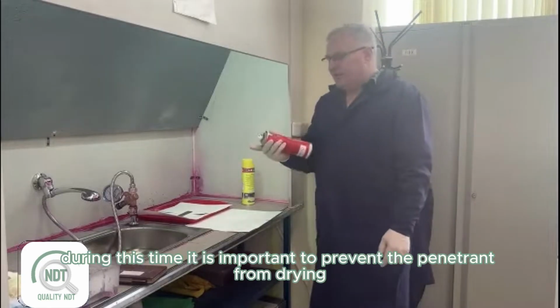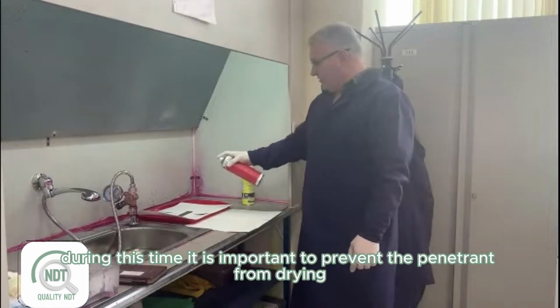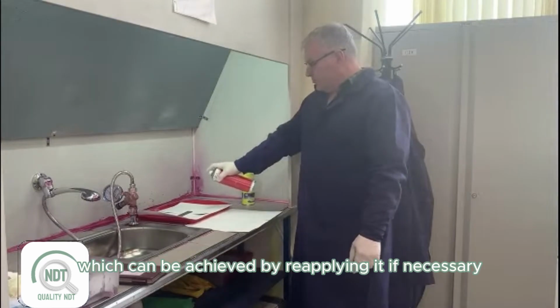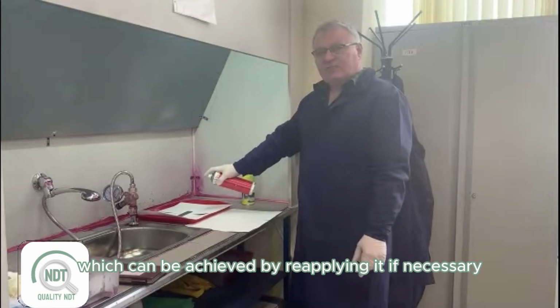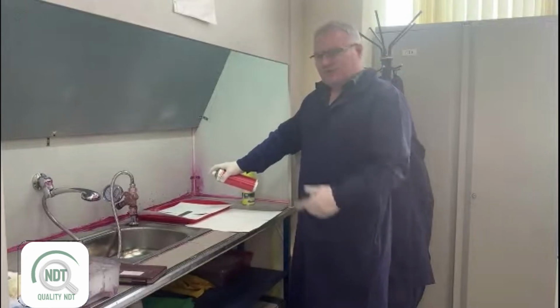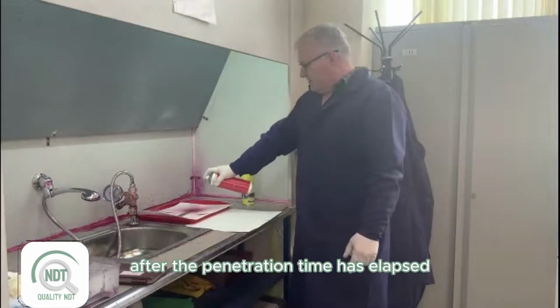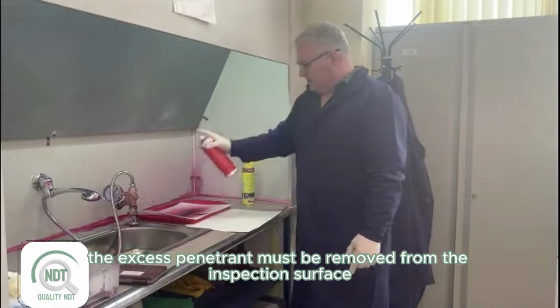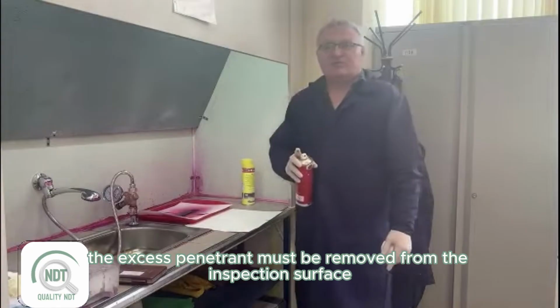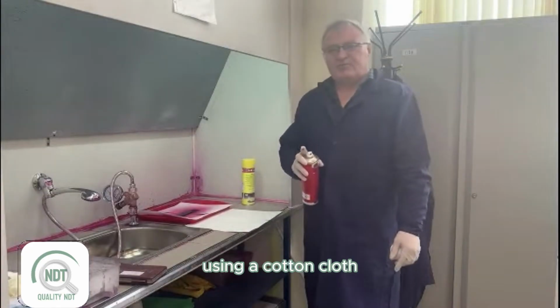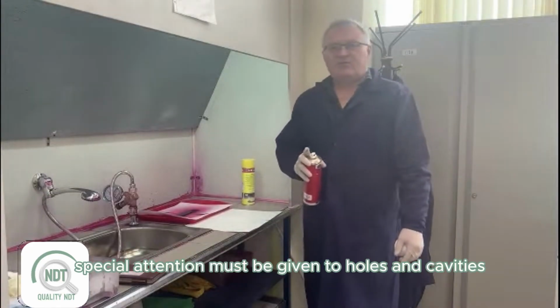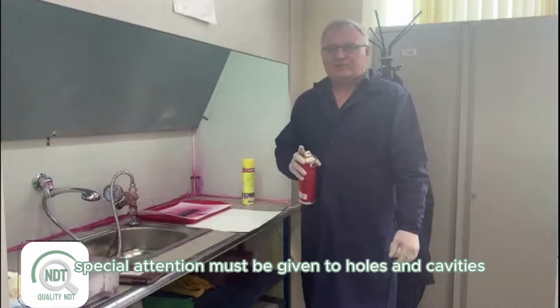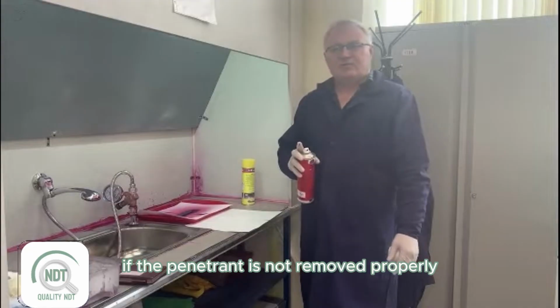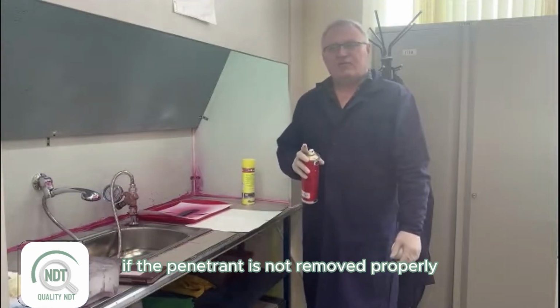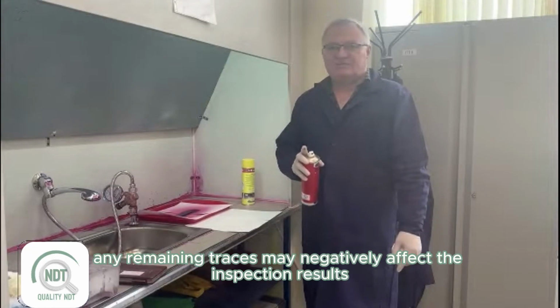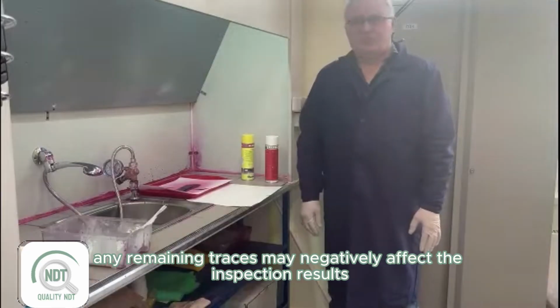During this time, it is important to prevent the penetrant from drying, which can be achieved by reapplying it if necessary. After the penetration time has elapsed, the excess penetrant must be removed from the inspection surface using a cotton cloth. Special attention must be given to holes and cavities. If the penetrant is not removed properly, any remaining traces may negatively affect the inspection results.